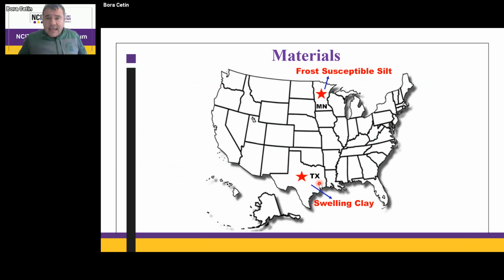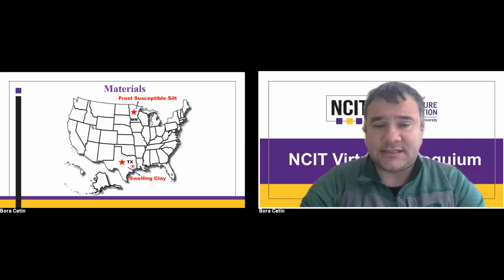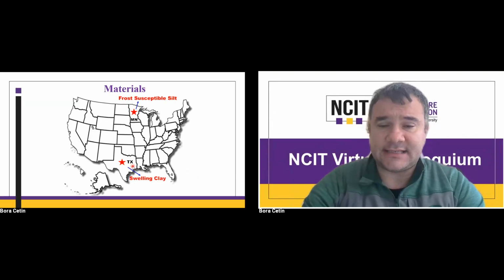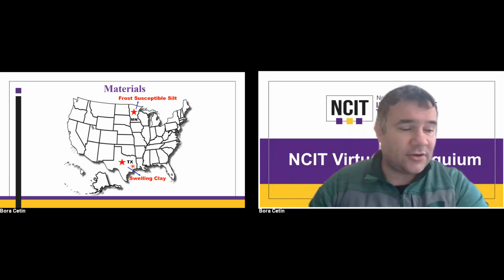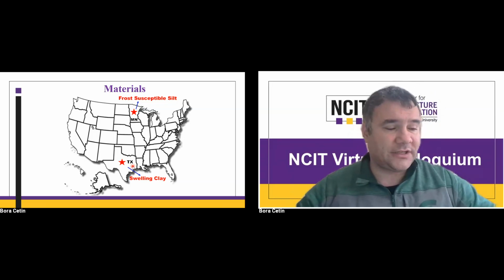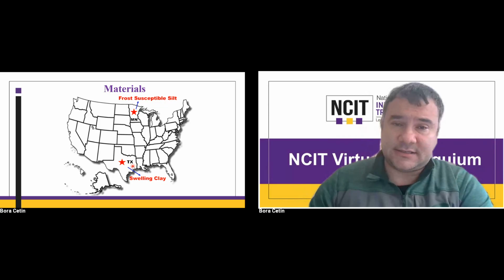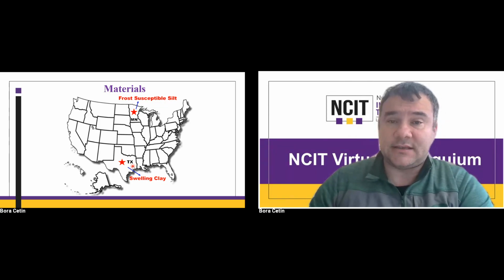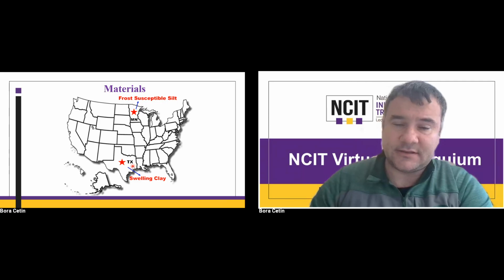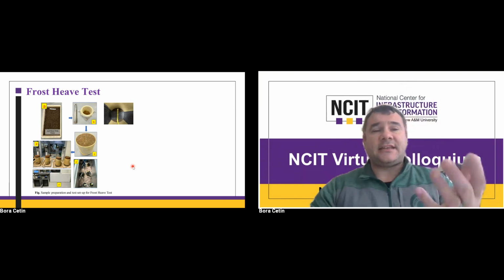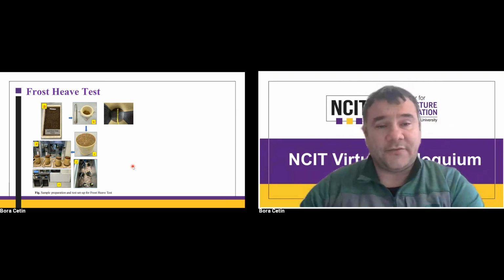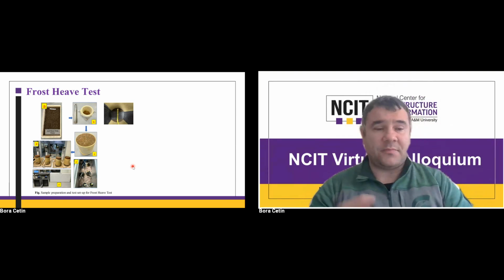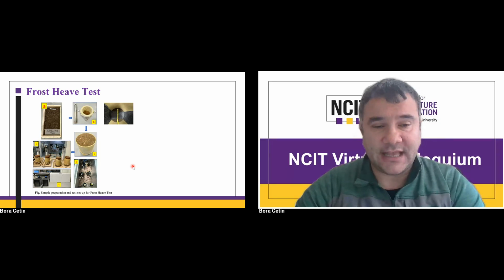So we collected two different soils, one from Minnesota, a frost susceptible silt, and one from Texas, a swelling clay, as our main goal is really to improve the performance of soils in freeze-thaw conditions and expansive wetting and drying conditions for the swelling expansive clays. And at MSU, what we mainly do is frost heave test. Again, I'm happy to provide more information on this later on.